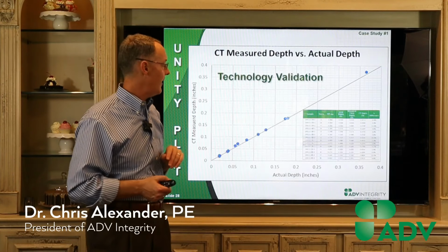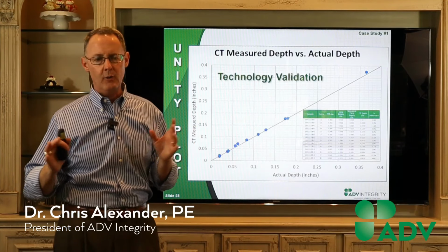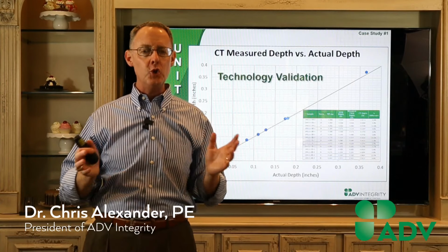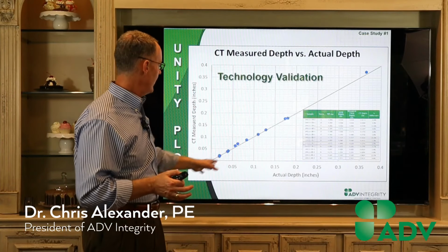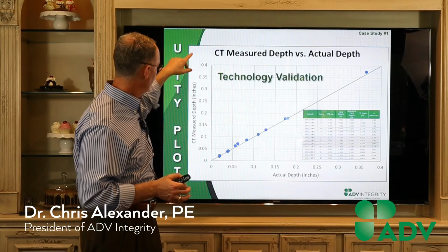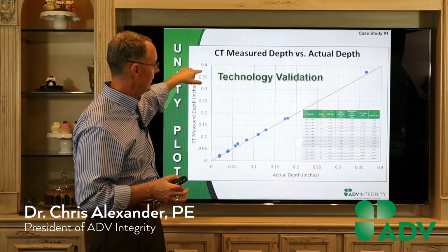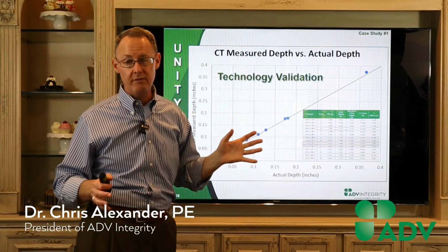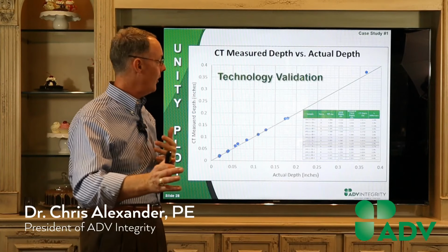And that's what this graph shows. So those of you who've done any kind of statistics, you do what's called a unity plot. You just draw a straight line, and we're measuring all the way from 0.4 inches. The pipe wall here was 0.375, so we actually had one feature that went all the way through.